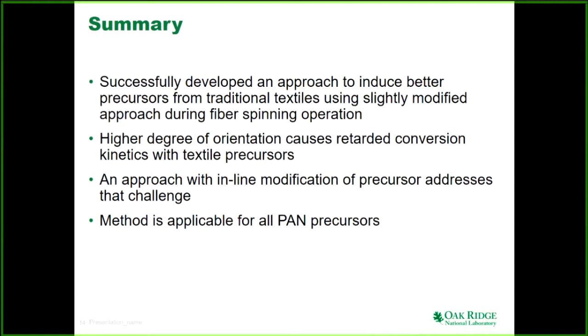A higher degree of orientation causes retarded conversion kinetics with textile precursors. We agree that textile PAN as such doesn't have the auxiliary functional group, that's why it is retarded. So we have learned how to address that. And with this approach, this inline modification, we will apply some sort of finish solution to the fiber, so that it would kick in some early stage reaction, and then it would help you to stabilize it quickly. And this method is applicable for any sort of PAN.